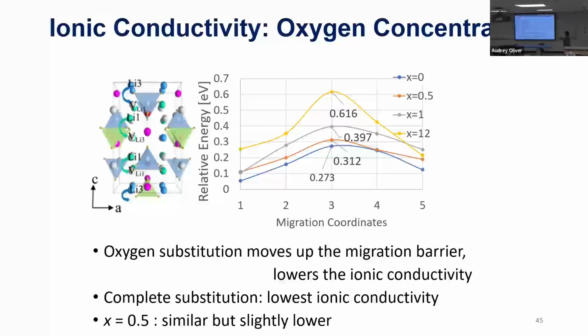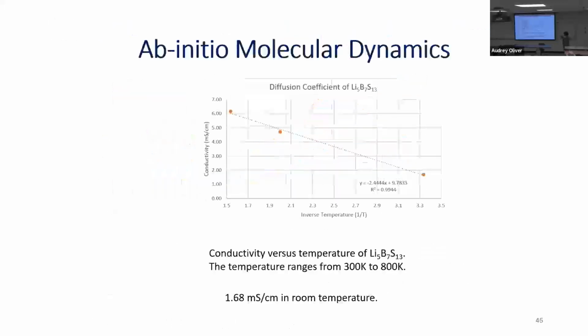You'll see there, for example, here, this is the migration barrier for the pure system and the doped system. If sulfur is completely replaced by oxygen, there is a large barrier, so conductivity decreases. It's not useful. But if you have some partial substitution, we can get relatively good ion conductivity. Using molecular dynamics, you can compute conductivity as a function of temperature, for example.